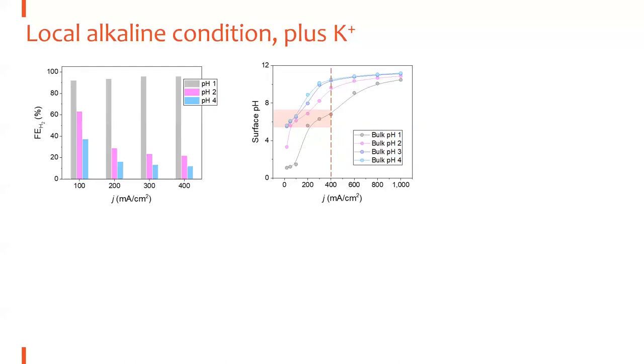This is understandable. But if we look at bulk pH 1, the local pH is roughly the same as for the other bulk pHs. And in order to achieve this pH, you only need a current density of 200, 300, and 400. So that means it's actually this column and this column. If these columns work for reduced proton reduction, this data point should also work. That means the column height should be much lower, because we can still have some CO2 being reduced with suppression of hydrogen evolution. But this is not the case.